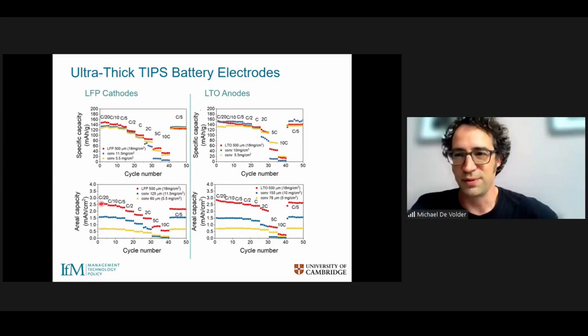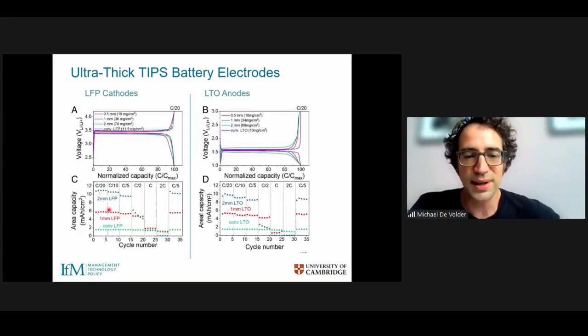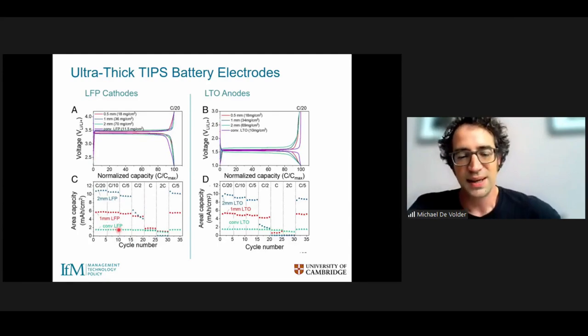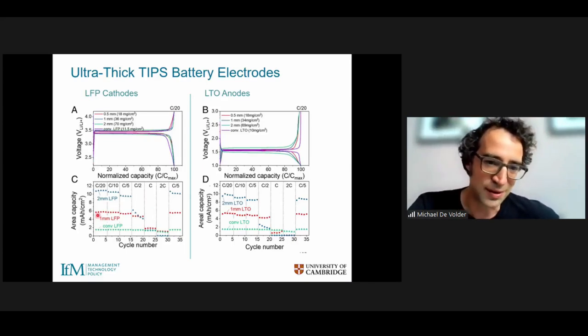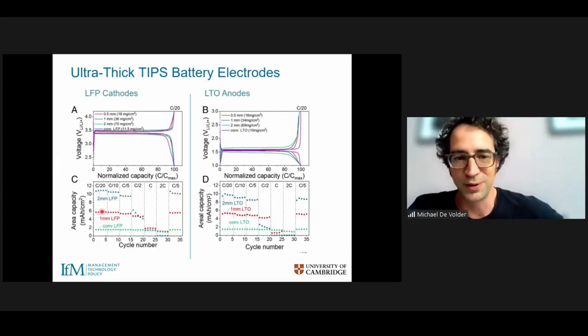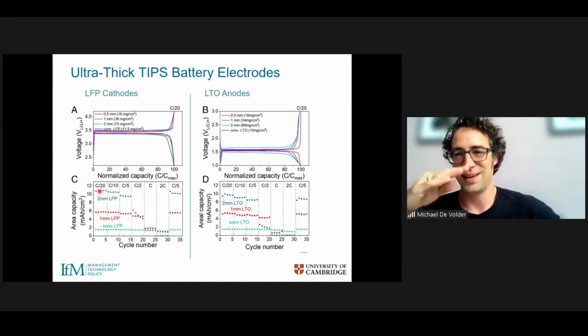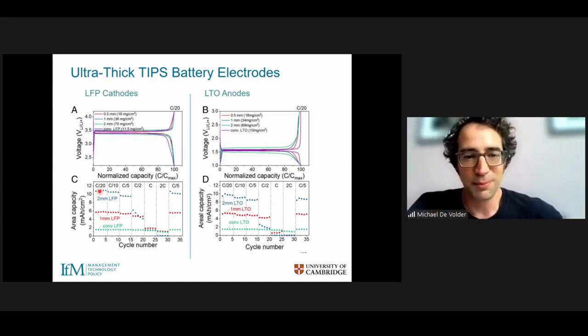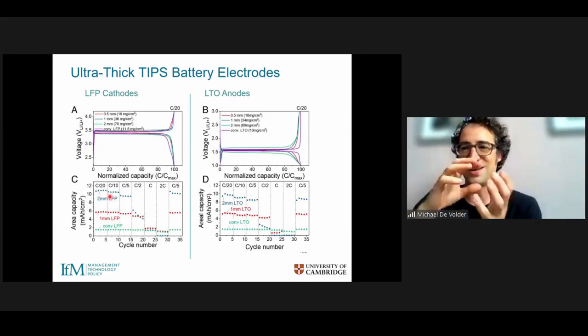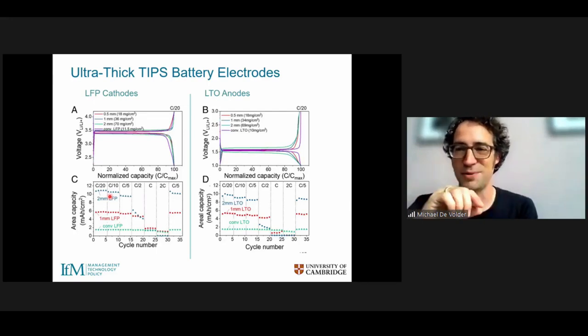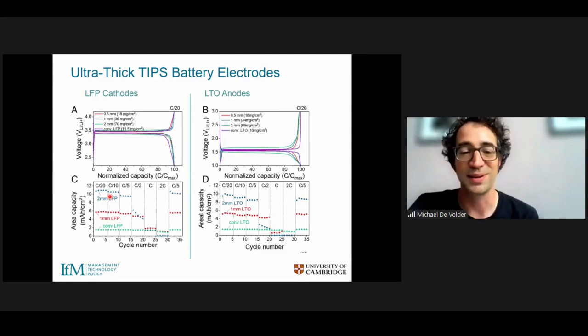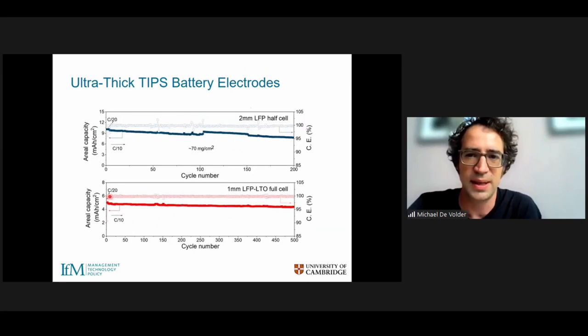So the question is, what happens if you make electrodes even thicker? Here you can see the conventional electrode in green. If we go to 1 millimeter instead of just half a millimeter, we can have a threefold increase in performance. And then if you go to 2 millimeter thick electrodes, we can double the capacity again. We weren't able to go to more than 2 millimeters because the casing of the batteries, the little coin cells we are using, doesn't allow for electrodes more than 2 millimeters thick to be inserted. It just shows how, using this phase segregation process, we can really change the properties of these batteries quite substantially.